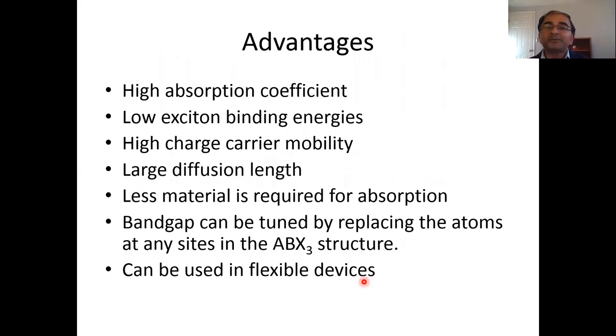What are the advantages of perovskite materials over organic and inorganic materials? High absorption coefficient. The absorption coefficient is very high, and if the absorption coefficient is very high, you need less material for that, and you will get high efficiency out of that. Low exciton binding energy. I told you that an exciton is a bound electron-hole pair, and if the binding energy is low, you will easily dissociate it. So it has lower exciton binding energy than organic and inorganic materials. High charge carrier mobility. The charge carrier mobility is very high. Diffusion length is large, so the carriers can travel a large distance without recombination.